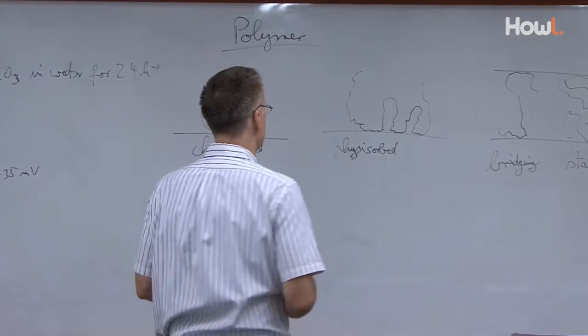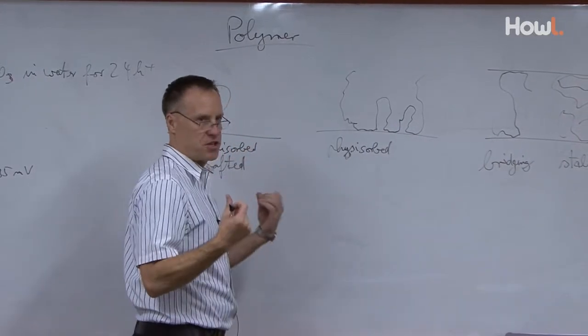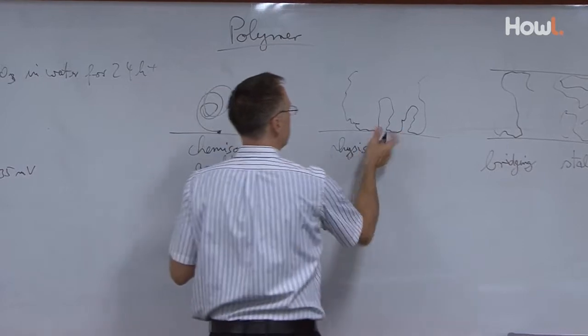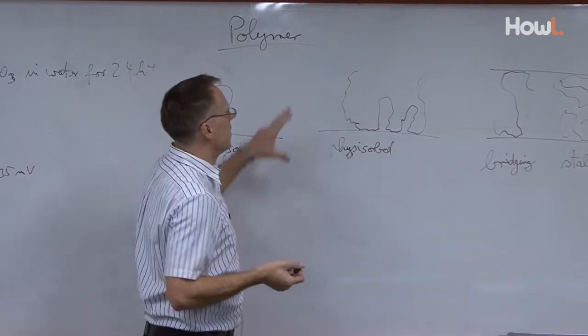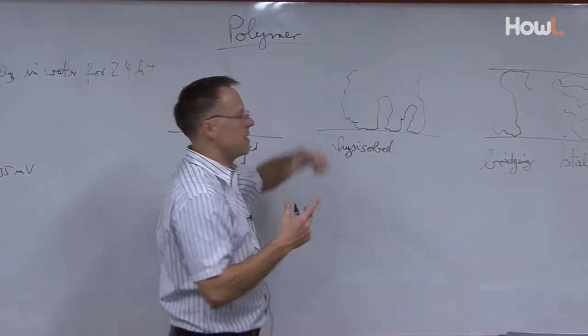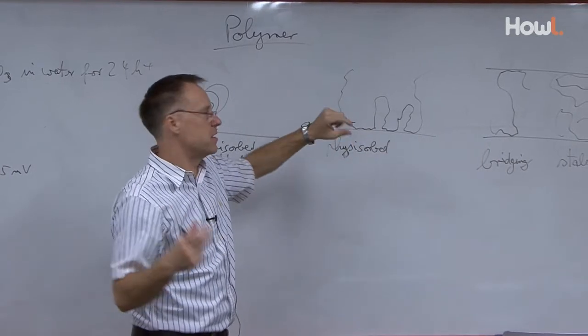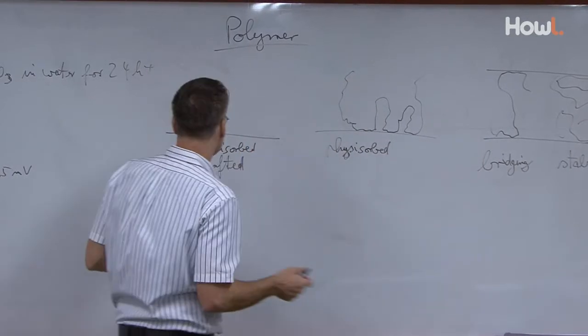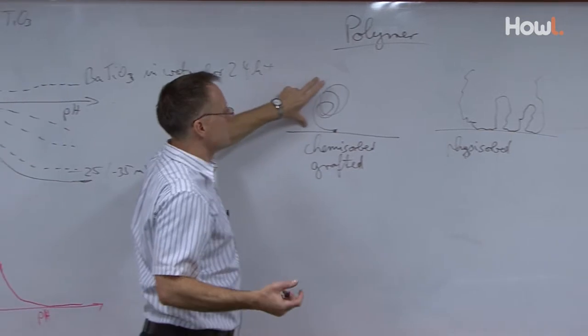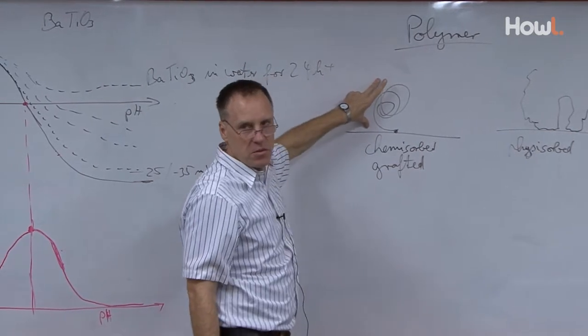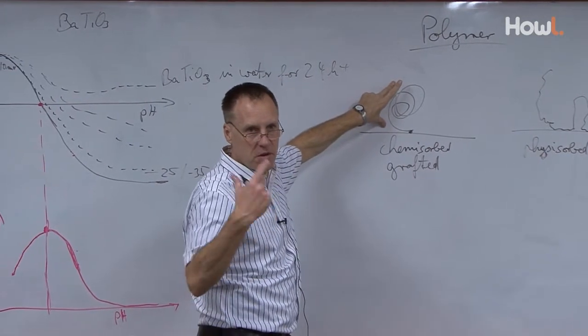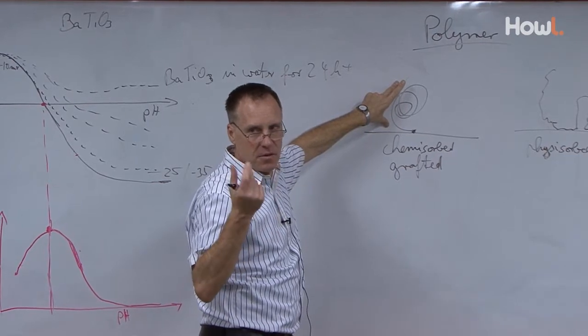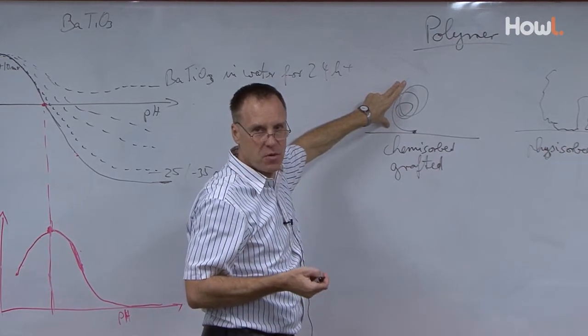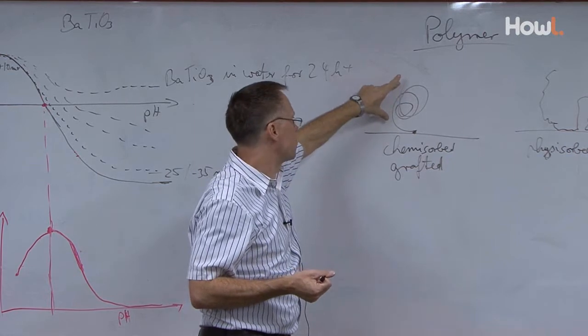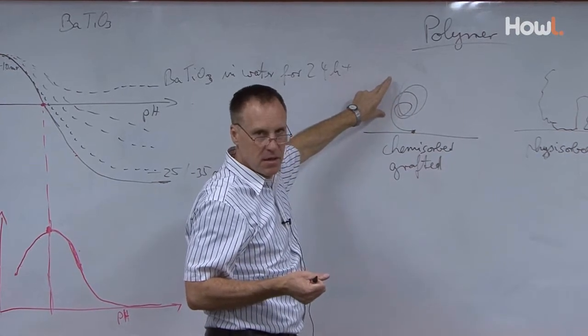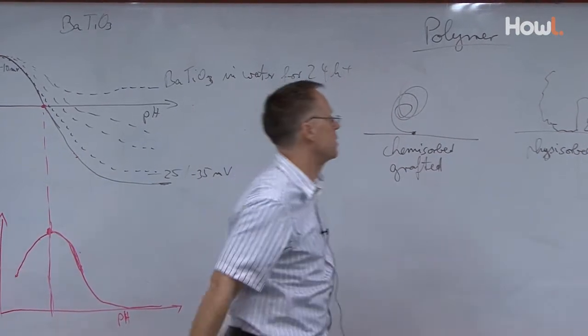And what you do, you force systems typically into specific shapes. And you see the physisorb molecule here is a little bit more flat usually than the entire coil. So you can calculate it's really much flatter. The chemisorb is just also like a coil. So you're getting the advantage of the statistics of the coil, but you still can do something about it to force it. You basically want to put an entropic effect into the system to push it out and deform it.